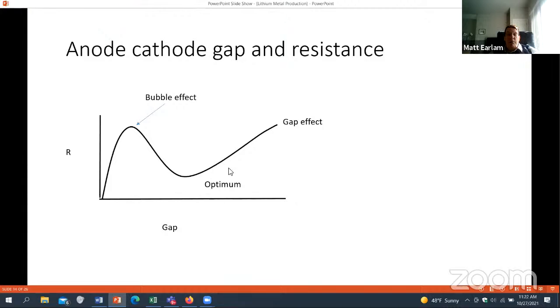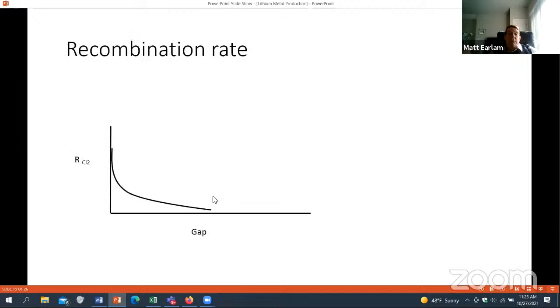And so there's an optimum resistance somewhere in here that minimizes the gap, the optimum gap. And this number is somewhere between 1 and 3 inches, probably about 2 inches, maybe a little tighter, depending on the load. The other thing that happens is you have recombination, obviously, you have chlorine reacting with the metal. And so the closer the gap is, the more contact you have with chlorine and the metal. And so your recombination rates are really high, which means your current yields up here are very small. They get better down here.